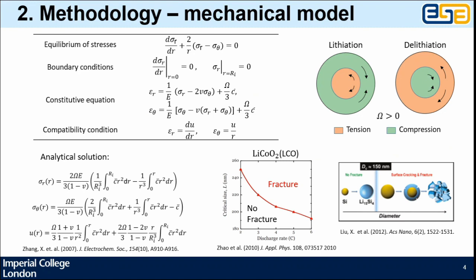We built the mechanical model at particle level based on the equilibrium of stress. It assumes that the increase of lithium concentration can cause mechanical strain, so from those equations we can get an analytical solution of stress and displacement. From the solution, we know that the magnitude of stress is a function of the particle radius and the lithium concentration, while the displacement is a function of particle radius and average concentration.